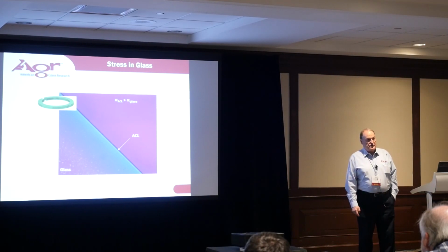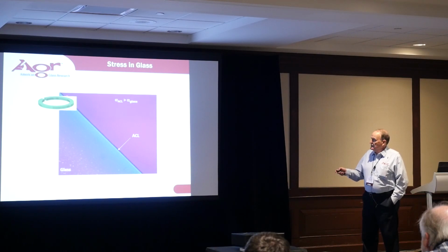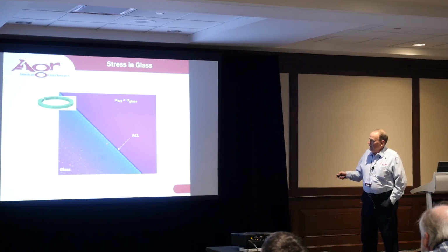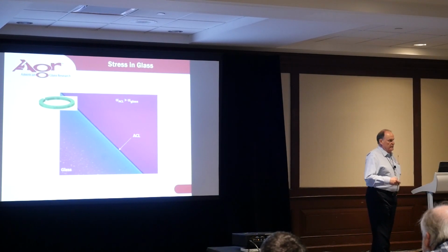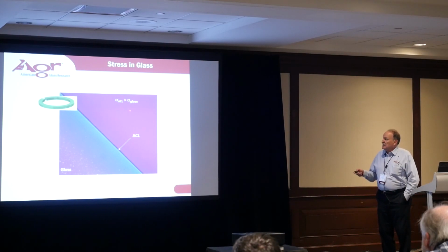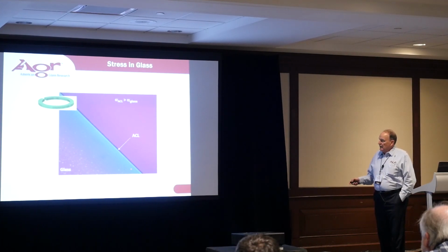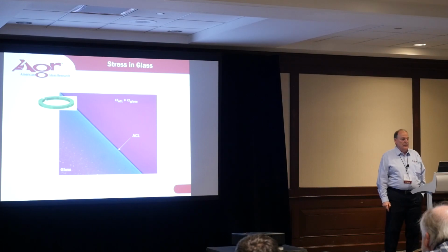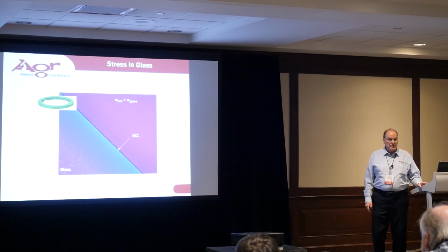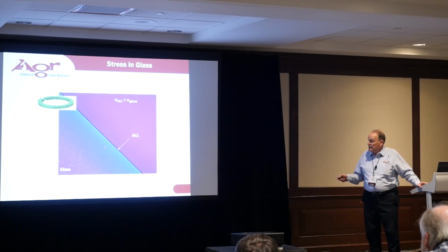This is a view of one of these ring sections in our polarizing microscope. This black line here is the ACL. By the way, we're looking down on the top of this surface here. The glass is to the lower left. The inside surface is out of our field of view down here to the lower left. This magenta colored region up here is simply the immersion fluid in which we have placed our ring section to view it. In this particular situation, the coefficient of expansion of the ACL is greater than the glass. By knowing how our microscope is set up, we know that this blue color is indicative of a compressive stress. As I mentioned before, through the use of suitable compensators on the polarizing microscope, we can measure the magnitude of that stress very easily.